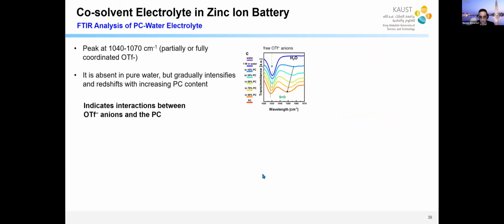Of course, we studied this spectroscopically in more detail, and I'll show you just a couple of examples. This is water right here, the blue, and you add PC to it all the way to 100% PC. When you first have the triflate in water, there are no peaks here, but when you add PC, a peak starts showing up. This peak is a result of the interaction of the triflate with the PC. Similarly here, you see a shift in the free OTF anions. That means when you introduce the PC, they are no longer free.